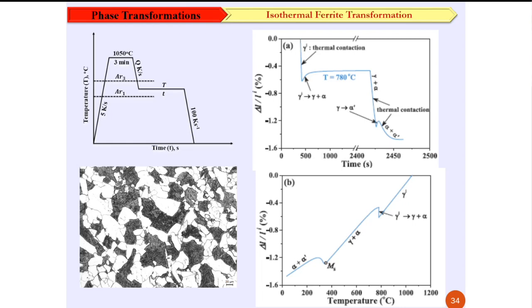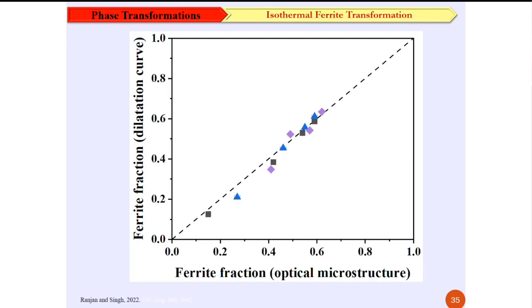We separated out and repeated our analysis, breaking the carbon concentration into the two morphological variants. We found that films of austenite have twice as much carbon as the blocky austenite. Atom probe analysis in recent months has confirmed our results that film austenite has twice as much carbon as blocky retained austenite after bainite transformation. To validate our model, we took an alloy transformed between A1 and A3 temperature to allow some ferrite to form, then compared ferrite fraction from optical microstructure with that calculated from the dilatation curve, finding a good match. The MS temperature predicted also showed a good match, confirming confidence in the method.